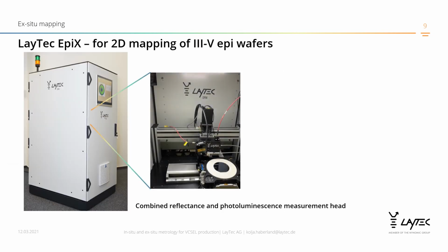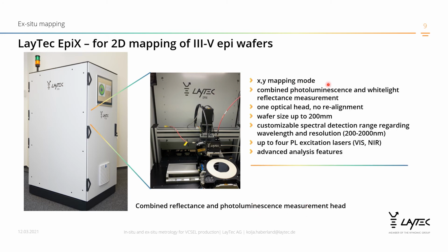The mapping system combines reflectance and photoluminescence measurement, and allows an XY mapping of the complete wafer with one optical head and no realignment for wafer sizes up to 200 millimeters. The spectral detection range is customizable in the wavelength range between 200 and 2000 nanometers, and for the photoluminescence, different lasers are available. It all comes in a package with advanced analysis features.